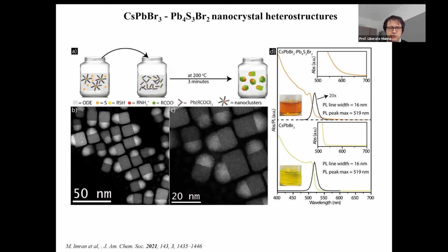And we mix them with all the precursors that are needed to nucleate and grow the chalco halide. And it turned out that in this synthesis, the perovskite domain nucleates and grows very fast, but attached to it, a chalco halide domain grows. And you see very little byproduct in this synthesis, just a tiny amount of isolated halide perovskite nanocrystals.